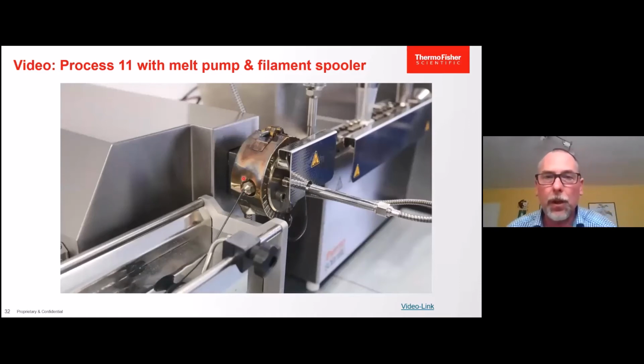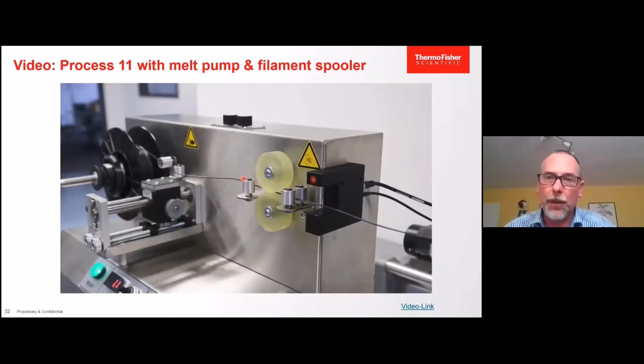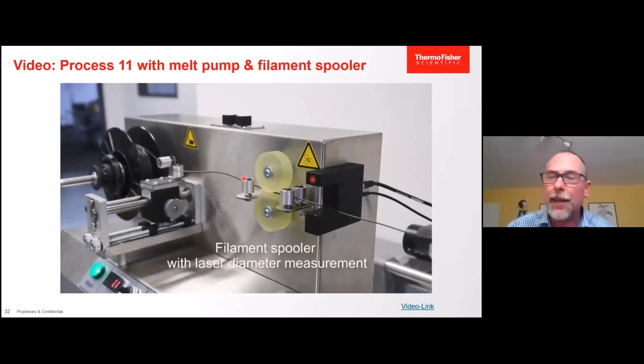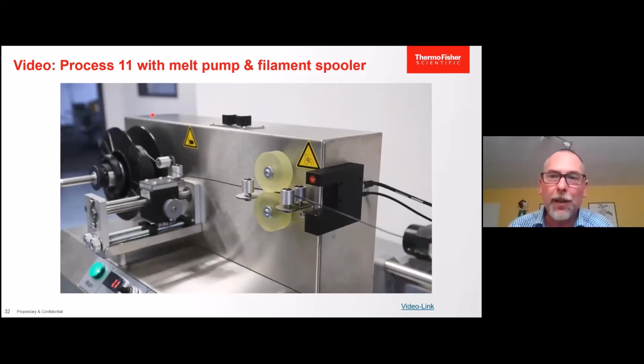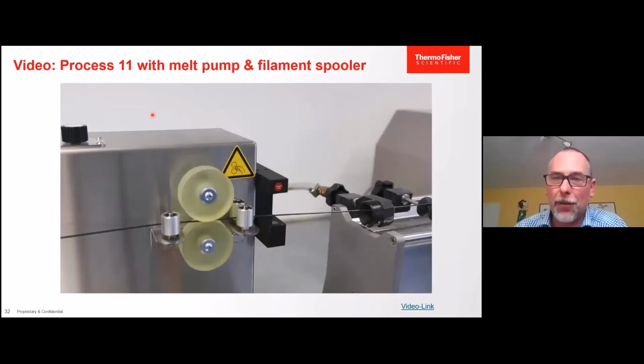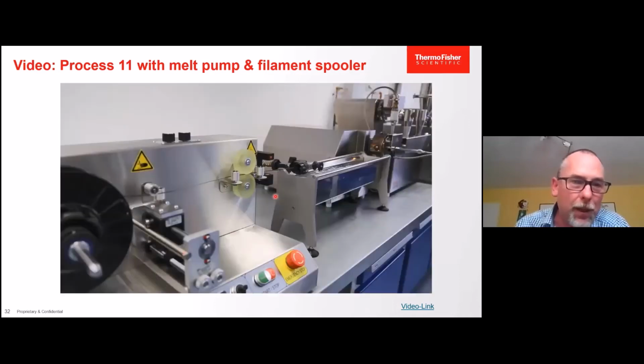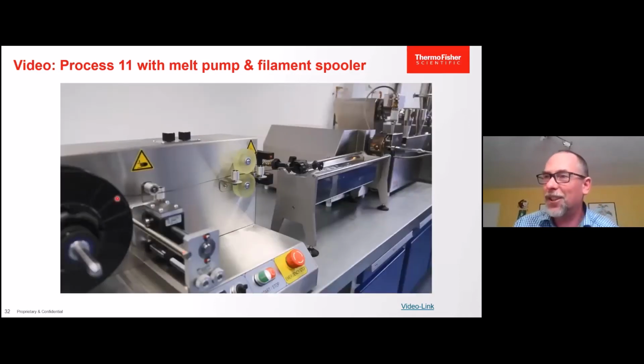It's important to know the diameter of the die nozzle is not necessarily exactly the final diameter, because we have die swell, or we are thinning the melt because we are pulling the strand, and when it solidifies there might be a change in volume. So finally we have to check the diameter here and adjust the extruder in a way that we get the desired diameter. And so here you see winding up the small strand.